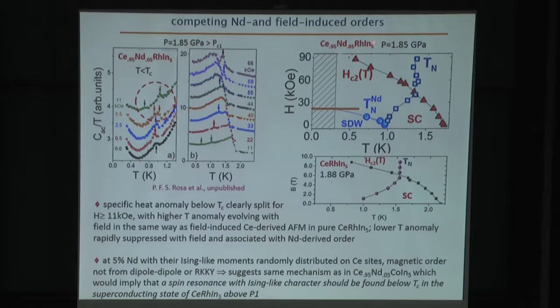So there's only 5% neodymium in this material. These neodymium atoms are just randomly distributed on cerium sites, and so it's very unlikely that the neodymium alone is inducing some direct dipole, or for that matter even RKKY type of magnetic order. And because, at least so far as we know, this magnetism develops only in the superconducting state, it again would suggest that this neodymium-induced magnetic transition has the same origin as the neodymium-induced magnetism in cerium cobalt indium 5, namely the condensation of excitons in a spin resonance.